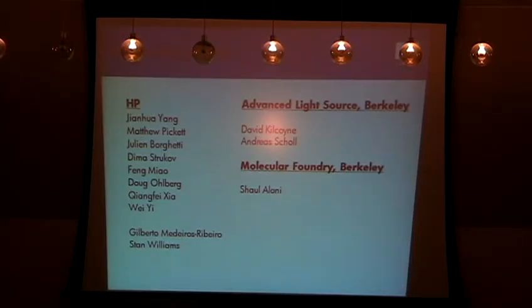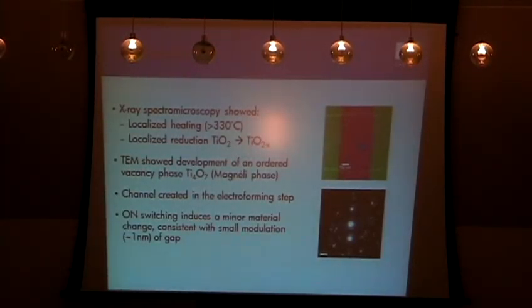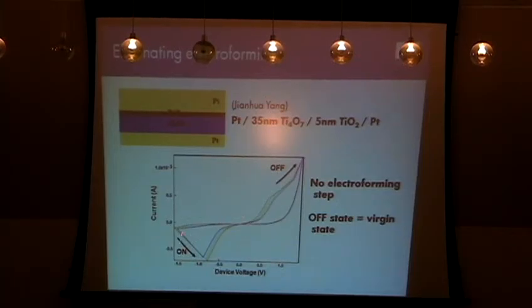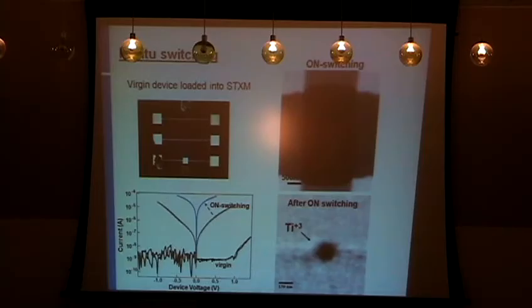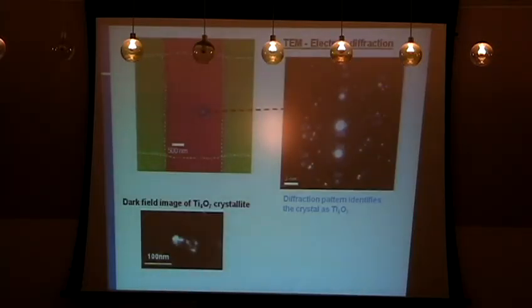Question: So what happens in an off-state? So as far as we can tell in the off-state, as you can see in this device, for example, the off-state is identical to the virgin state. So in this case, in the sample, when I went to switch it off, I actually broke the sample. The heating that was necessary broke it. So as far as we can tell, any kind of change in the off-state—Stan mentioned that most of these devices break from the heating. Well, that's even more true when you build it on a membrane. You don't have a good heating reservoir to get rid of it. So this sample that I did show over here, this had already been cycled on and off many times, so it's not clear. But as far as you can tell from the electrical data, this is a very small change in the conductive channel. It's just a change in the tunnel gap. So most of our information for the off-state is actually coming from electrical data.